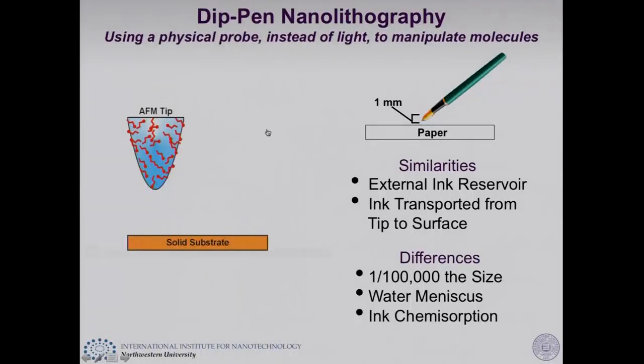One of the tricks is when you do an AFM experiment in air and you bring the tip down in contact with the surface, what naturally happens is water collects at the point of contact. That's viewed as a major problem in the field. And we looked at that and said, hey, wait, we could use that as a carrier solvent. And if we designed molecules that chemically reacted with the surface, when we brought the tip down and moved it across the surface, they would react in a self-limiting way with the surface and generate a structure one molecule high. And you're going to see that in cartoon fashion here. Now you've got to keep in mind, the size of this tip is 1/100,000th the size of a quill pen.